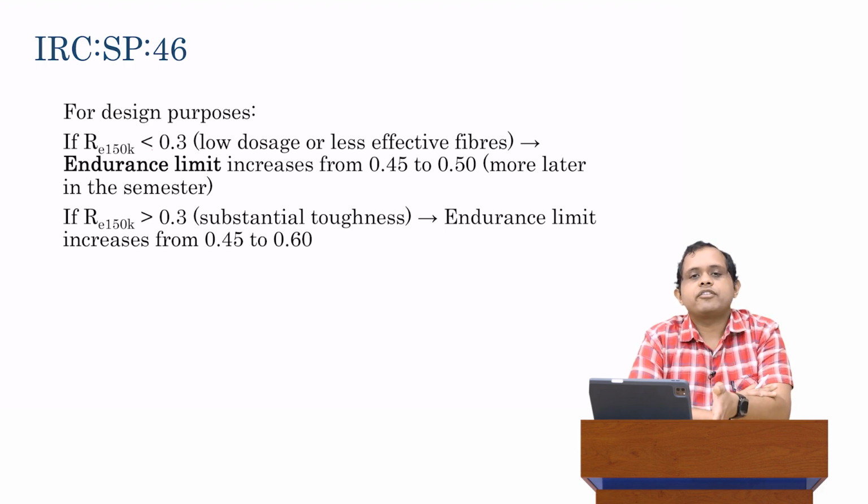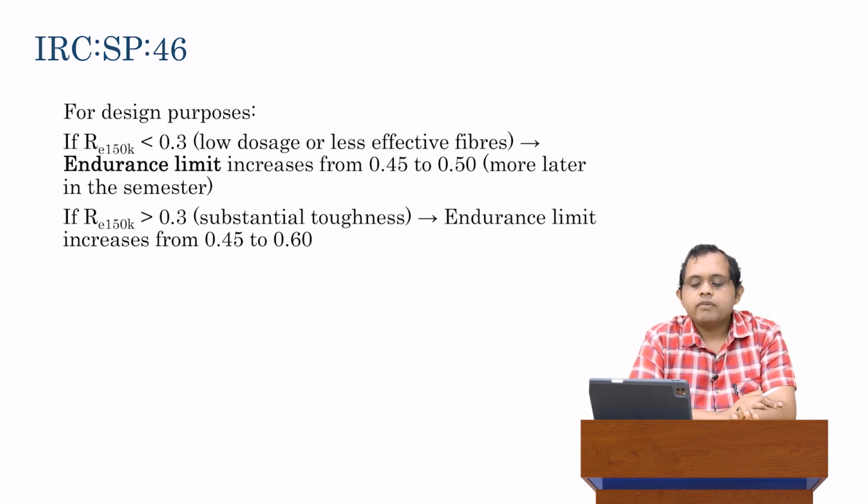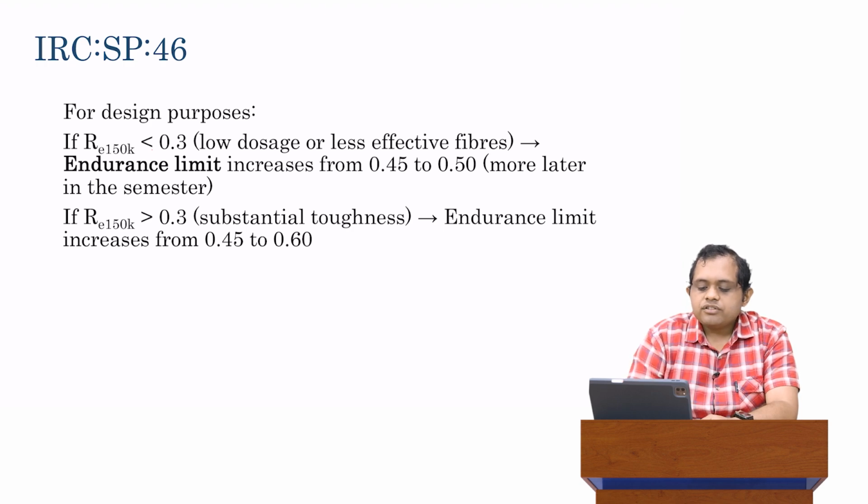Of course, you do it for the 95th percentile, hence it has to be the characteristic value. The most important recommendation which IRC SP46 makes is as follows: if the residual strength ratio is less than 0.3, that is, if it's low dosage or less effective fibers, then the endurance limit can be increased from 0.45 to 0.5.